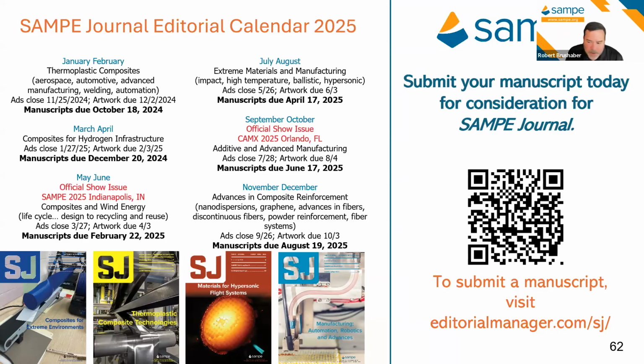There's one in here about cyanate ester resins. I actually used cyanate ester a long time ago. I want to point out, you need to examine the char yield. Cyanate ester does not have a very high char yield. Char yield is a definition that a lot of people use, but every researcher uses a different definition, so you cannot compare using the literature. So in our group, we solicit a lot of commercially available material, and we use the same definition for char yield, which is 20 C per minute in nitrogen. When you heat it up to 1000 degrees C, the mass remaining is the char yield. Cyanate ester in our lab has not been what I call a high char yield resin compared with phenolic and other resin systems. Thank you.